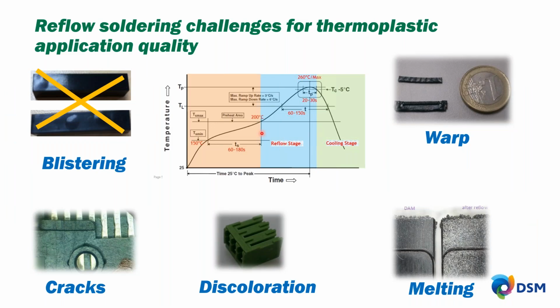So the reflow soldering process, you can kind of see here, is a relatively rapid heating up to around 260 C for the parts. So we have to withstand both the heating and cooling stage and the time at that high temperature. The plastics have to be able to withstand that. So what are the kind of defects you may see in that process? Blistering. Obviously, we talked about the MSL level. So that's a blister. This part obviously blistered through the reflow process.